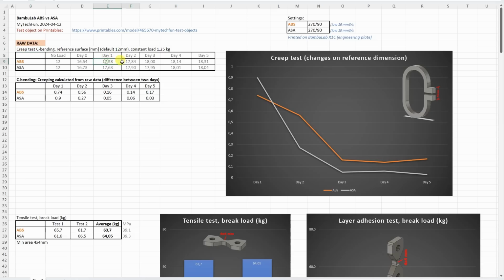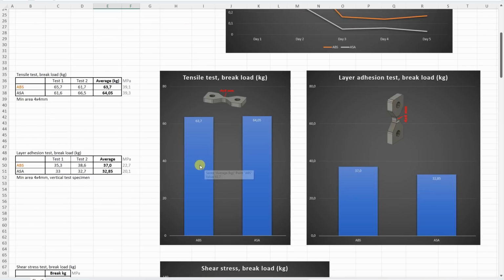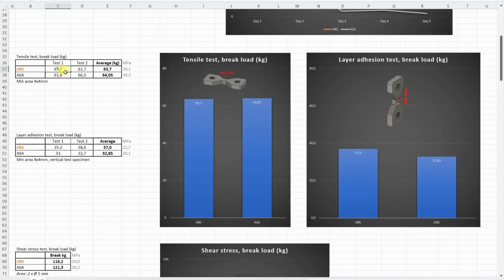So these are directly measured values, but what you need is difference between 2 days, and that's what we can see on this graph. And we can see even on the 2nd day I could record some creeping. Only on 3rd day it was reduced, and the ASA was better in this case, but this is also very good, very low value. On a tensile test, all break loads were very similar, and between these two they're almost equal, but this is a little bit lower compared to the average value from my summary table.